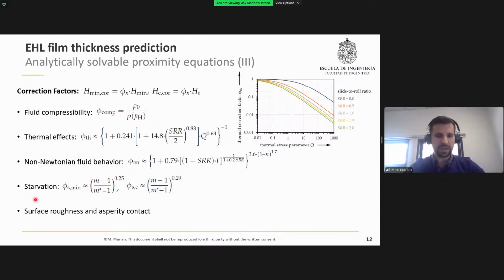And basically fully flooded conditions are reached when the distance between the contact inlet, where we allow pressure buildup, and the contact center ceases to affect the film thickness. And Dowson and Higginson basically suggested taking the fully flooded boundary M star and the inlet location of the contact into account to calculate some correction factors to also cover starvation effects.